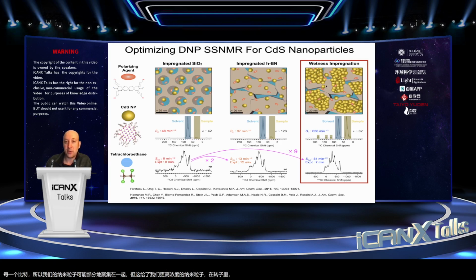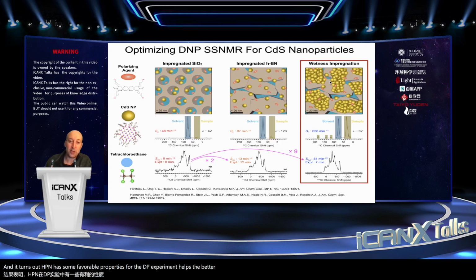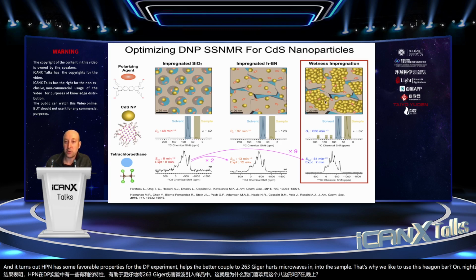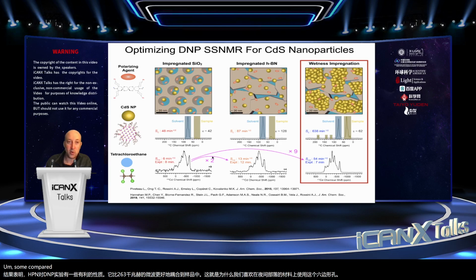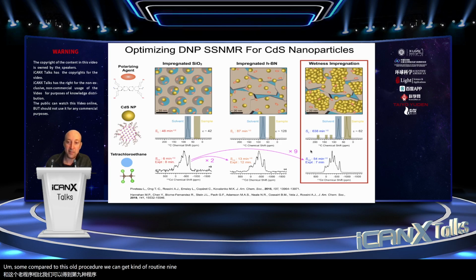And it turns out HBN has some favorable properties for the DNP experiment. It helps to better couple the 263 gigahertz microwaves into the sample. That's why we like to use this hexagonal boron nitride material. So compared to this old procedure, we can really get kind of routine 9 or 10-fold improvements in NMR sensitivity through the combination of increased concentration of the nanoparticles and better DNP enhancements.